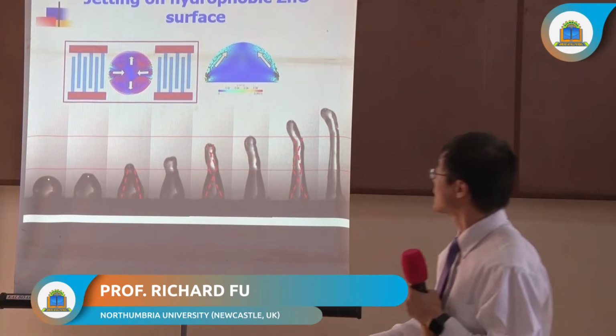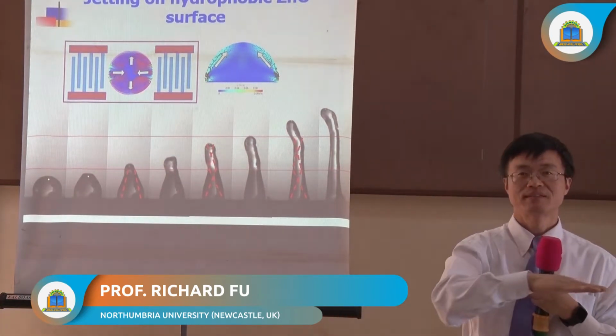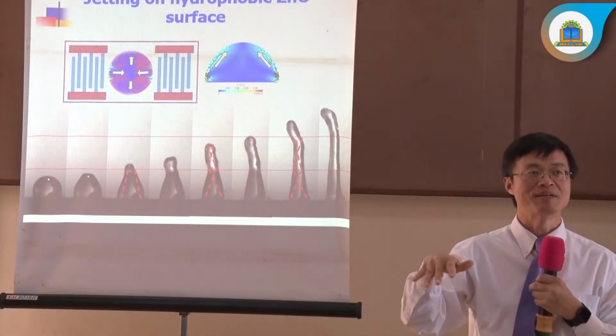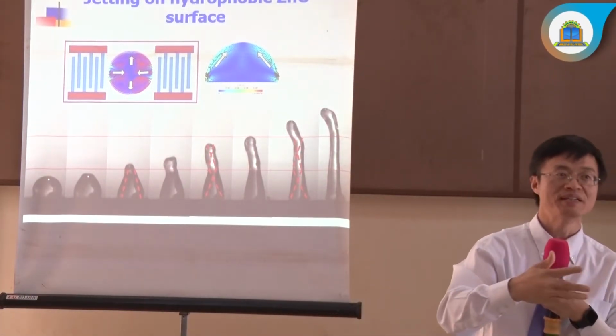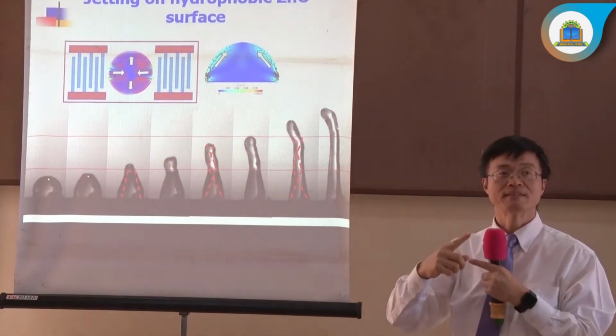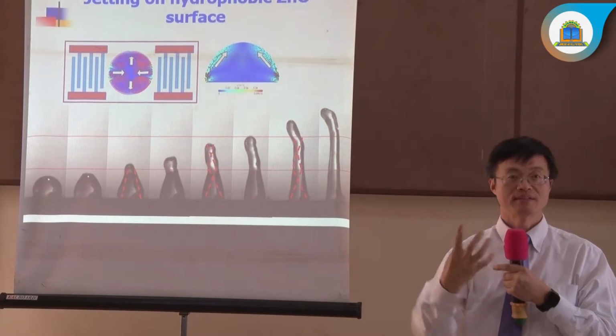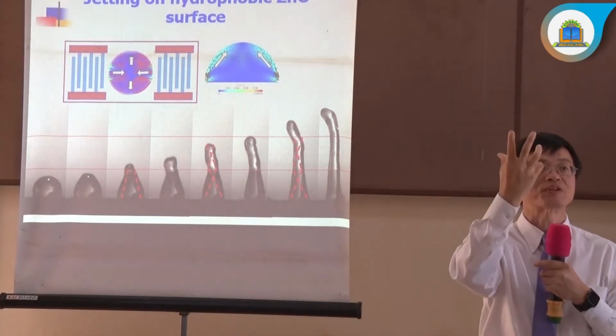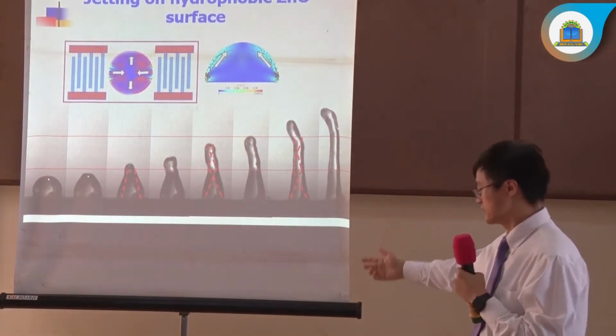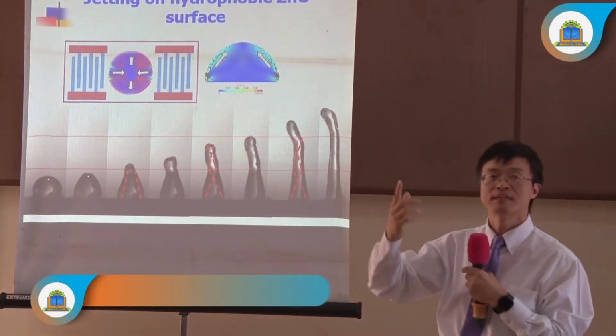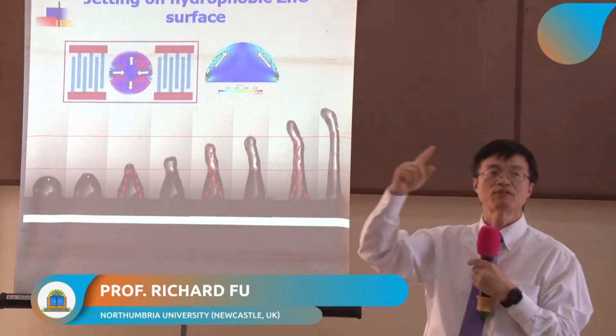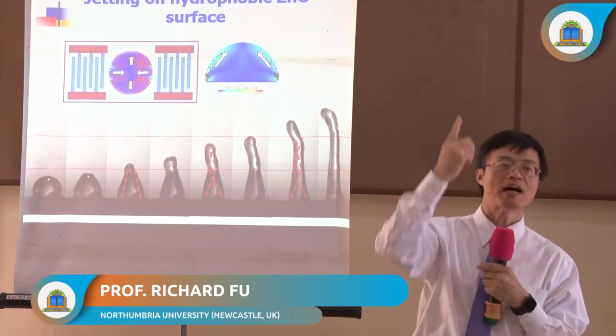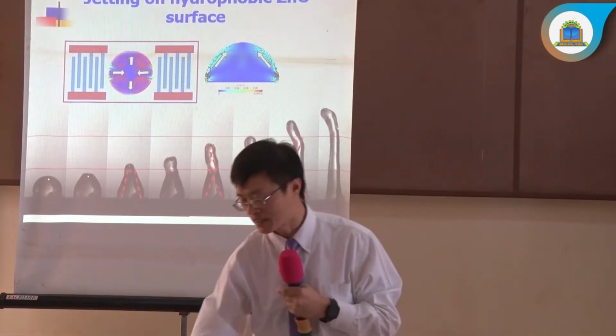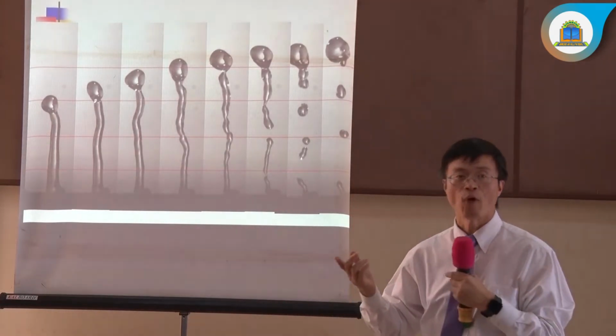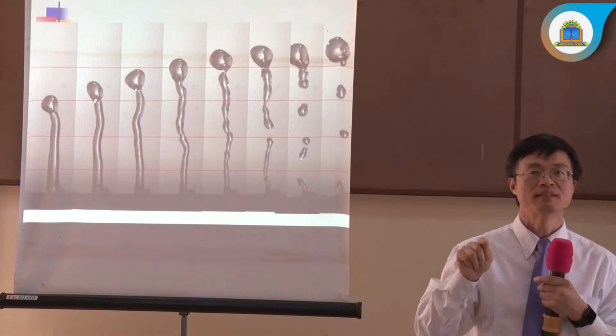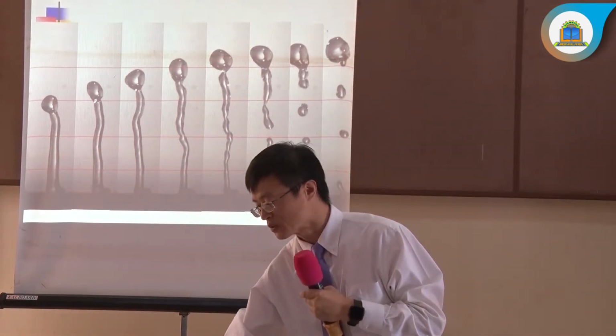Basically, it's quite easy if we have the wave from both sides. The wave from both sides we call a standing wave. The liquid has pressure from here and pressure from here, and then the energy into the liquid will balance in the x direction, right? The only direction the droplet can move is upward. So if you apply high power, the pressure from both sides pushes the droplet up, and the energy reflected to the surface deforms the droplet and pushes it further up, and up and up, and then you get the vertical jetting. So we can use this for printing vertically, with ink containing biomolecules or cells.